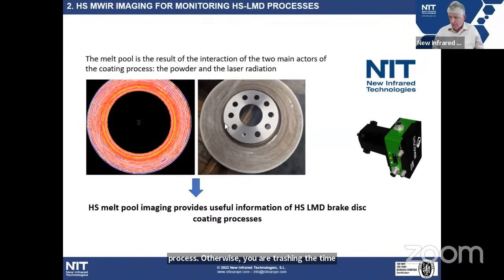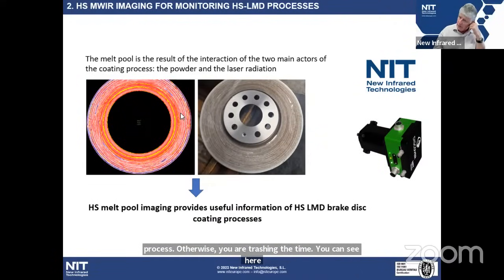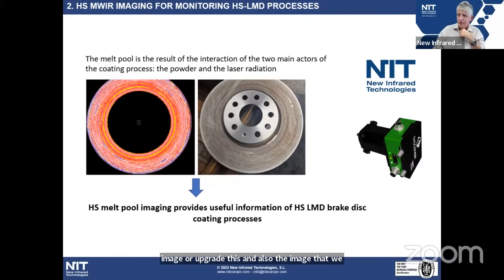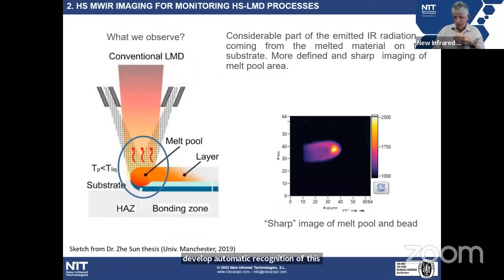You can see here an image of a brake disc and also the image that we can reconstruct using the melt pool. If you look in detail, we are able to reproduce with good resolution practically all defects in the disc. Now our challenge is to develop automatic recognition of this type of defect. In conventional LMD, all the powder is melted on the substrate, and we obtain a very sharp image of the melt pool. Don't forget that we are imaging at 1,000 frames per second. We take 1,000 pictures of the melt pool per second, and we extract some information.